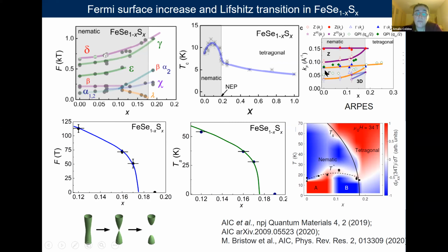And this is quite different from the ARPES data for the hole pocket, which show this anisotropy between the X and Y direction, and the presence of this additional inner hole band from about 11%, but there is no indication of a disappearance of the pocket. Moreover, here, slightly zoomed out, is the effect of superconductivity, again showing that at the nematic endpoint there's rather a drop, and the enhancement which exists is inside the nematic phase.